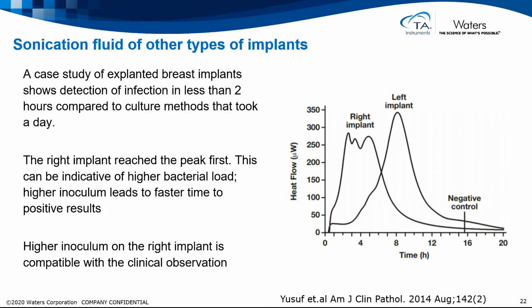The right implant reached the peak first, and this can be indicative of a higher bacterial load, as a higher inoculum will lead to a faster response time. This was also compatible with the clinical observation. So calorimetry can have a benefit when it's very critical to have a fast diagnosis or test of an infection.